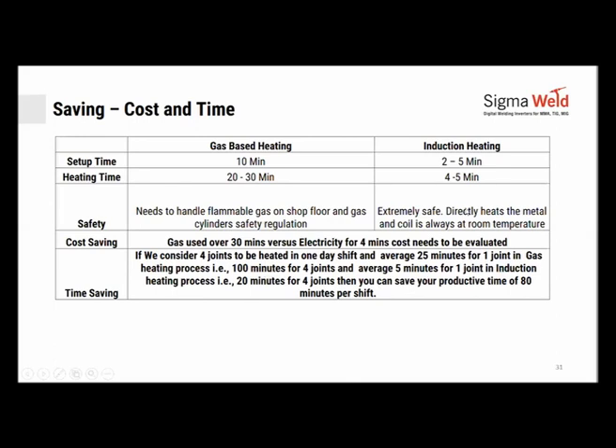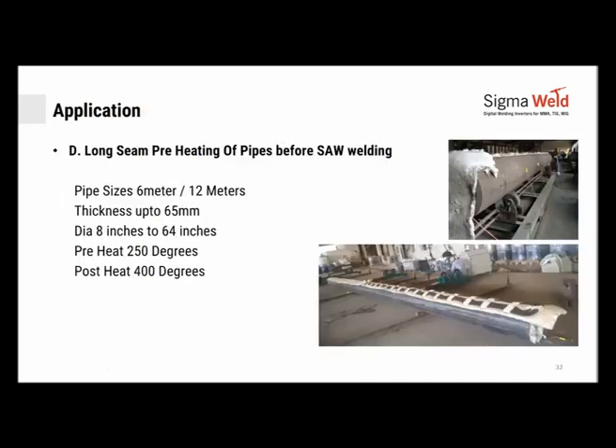5 minutes for 1 joint in induction to do preheating. You could have done 4 joints in 20 minutes. 100 minutes for 4 joints with gas, 20 minutes for 4 joints in induction. 80 minutes per shift, you can convert into productive time and get more jobs done. Same manpower, same equipment, more jobs done per shift.